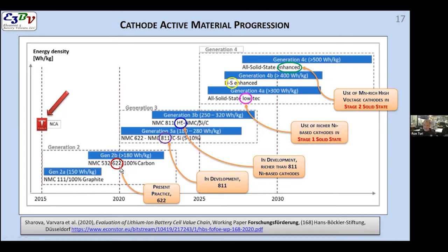And as you see the nickel content coming up, the first digit is nickel, the middle one is manganese, and the third one is cobalt. As the nickel content comes up, the energy density comes up, and there are a lot of reasons for that. We can talk about that as a separate thing too. That's a topic all unto itself. Nickel is a great thing because it's very labile in the crystal and gives you a lot of access to the lithium that it contains. And you can get more lithium out of a nickel oxide at a given voltage than you can with some of the other oxides. That's why you see things climbing as you go to 80% nickel. And there are today 90% nickel formulations as well.